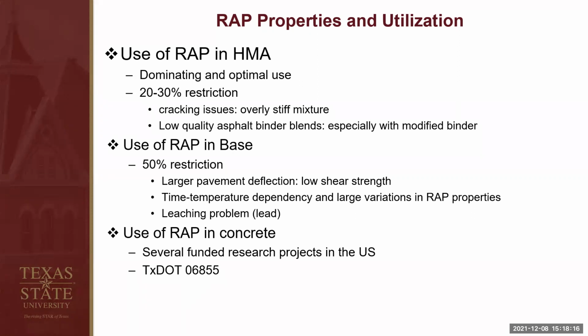And also nowadays, especially in hot climates like Texas, we use a lot of modified asphalt binder. If we add too much RAP in modifying to blend with modifying binder, then the blended asphalt binder quality will be low. So that's why most of DOTs in the United States only allow 20 to 30% RAP replacement level in new HMA for the surface courses. RAP can also be used in base. However, there's also a restriction, and typically the restriction is about 50%. This is because if we add too much RAP in base, then the pavement will have larger deflections because of the low shear strength of the RAP.